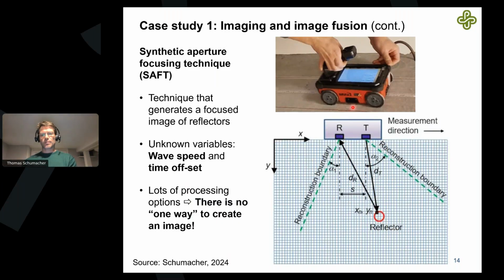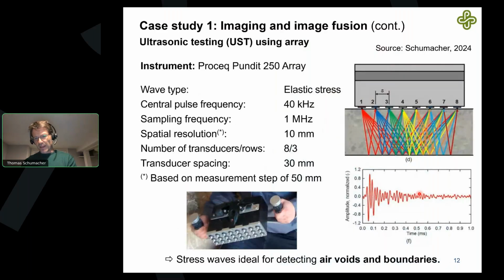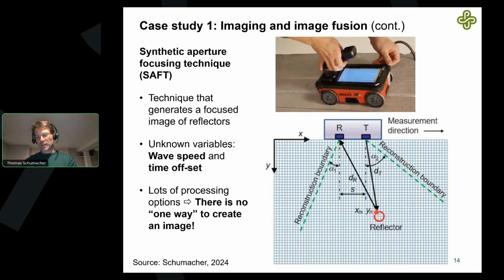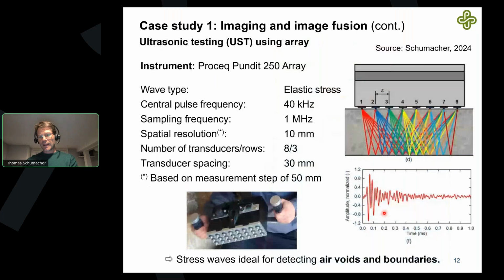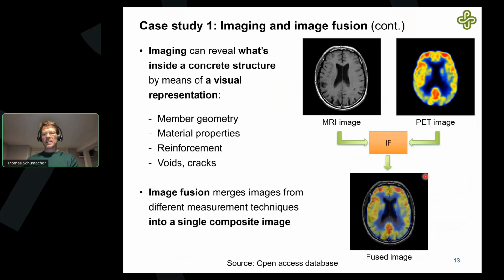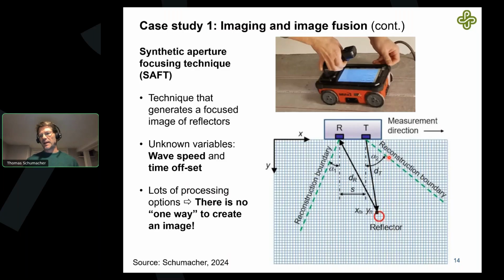And now for the signal that corresponds to this measurement position, I go into the signal and read out the amplitude, which could be right here, for example, and I then map that amplitude value back to this point. Now I do that for all the different points in this domain, for all the measurement positions, and I add it all together. If my point happens to be on a reflector, then hopefully there will be a big amplitude in the signal that reflects that reflector. So we're basically focusing with the SAFT method, trying to get the reflectors to show big amplitudes focused on them.